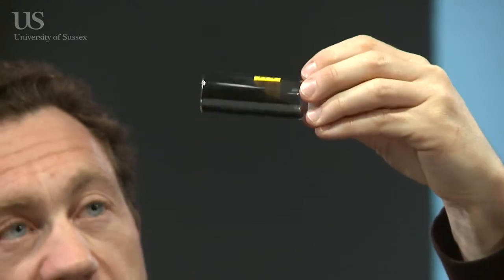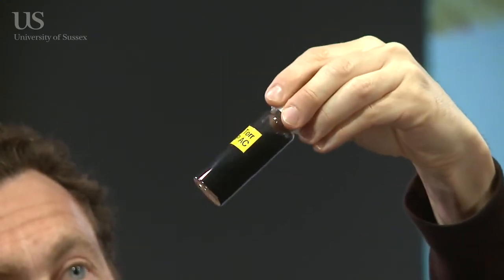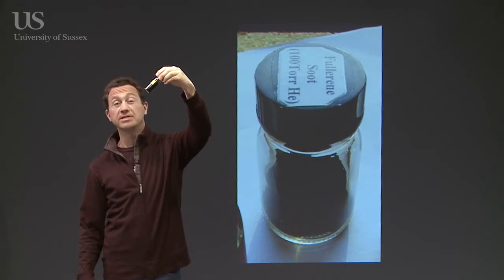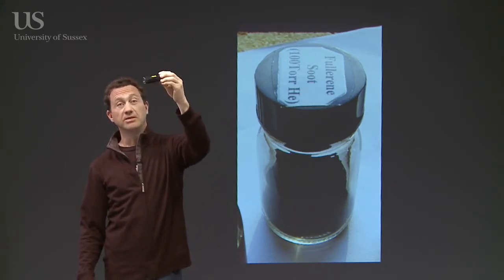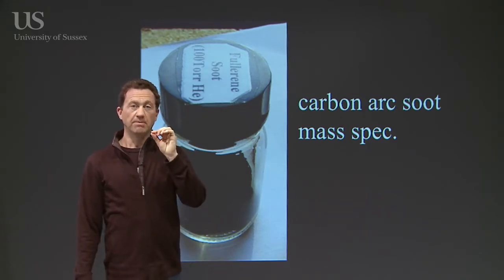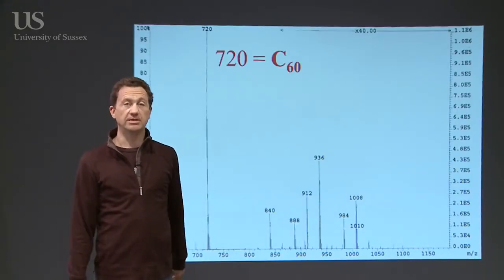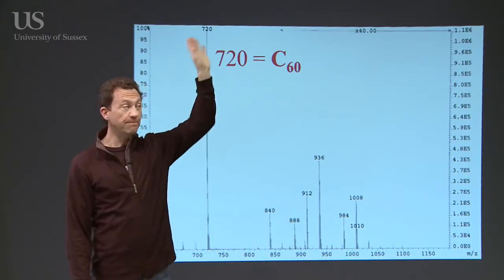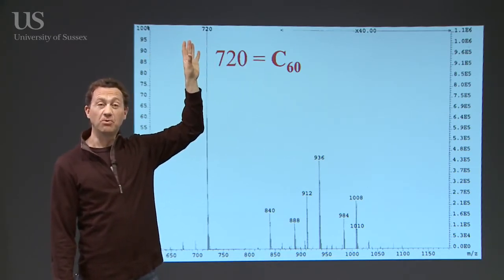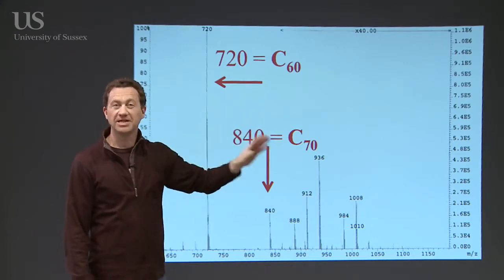This little glass jar is full of this sort of black soot-like material, and it's pure carbon — we're vaporizing pure carbon rods in helium with no oxygen, so we don't expect any oxides. This is just vaporized carbon which has come back and formed this black sooty material. It turns out that 5% to 10% of this black sooty material is the beautiful C60 molecule — the buckyballs. If you put this soot into a mass spectrometer, you get a very beautiful spectrum with an enormous peak at 720 mass units — that's what C60 should weigh. You also see C70 in there, which is a rugby ball-shaped buckyball.